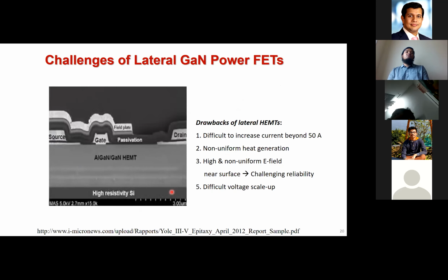Gallium nitride lateral power FETs enjoyed a tremendous success, but there are some drawbacks. Here on the left, we have a typical structure of a gallium nitride lateral HEMT, with the source on the left, the gate in the middle, and the drain on the right. Since it's a power device, we have a long drift region, and the device is asymmetric in blocking voltage. The first major limitation is that it's very difficult to increase the current beyond 50 amps in these devices, because one way to increase the current is to increase the area of the device, which increases the footprint, so the device becomes bulky if you try to supply very high current.